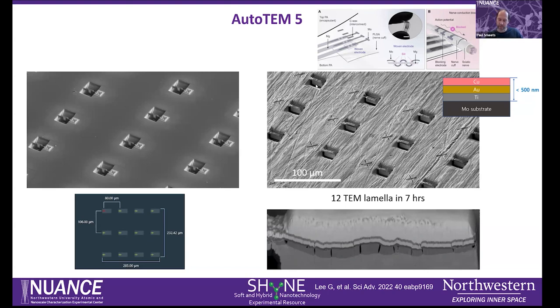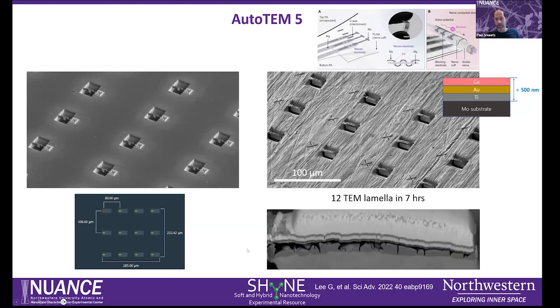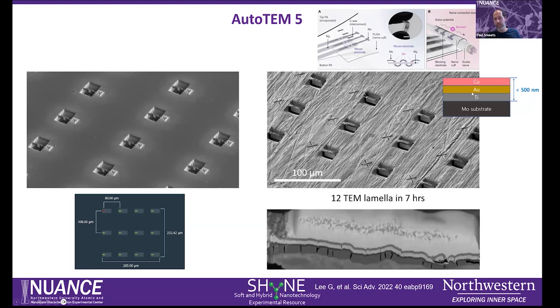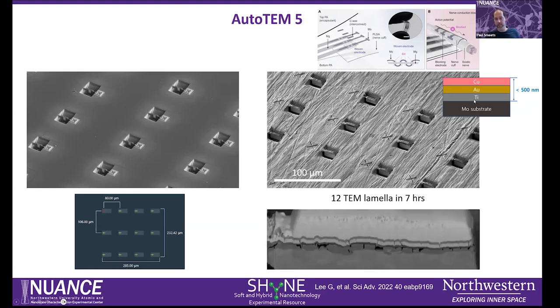Then I basically let the program run, and indeed I was able to create 12 TEM lamella in 7 hours in an automated fashion. And then I dove in with the EDS detector and analyzed the cross section to see what the variability of the thickness of these metal layers were.